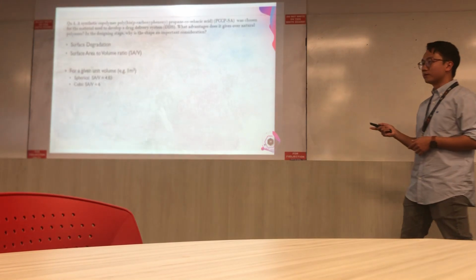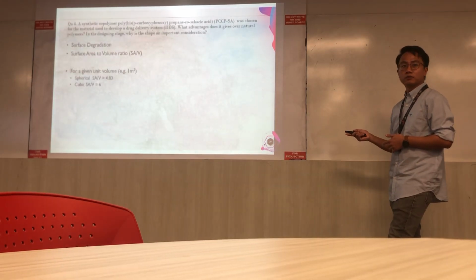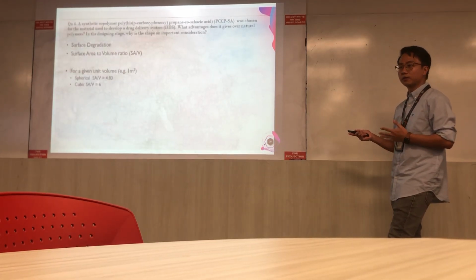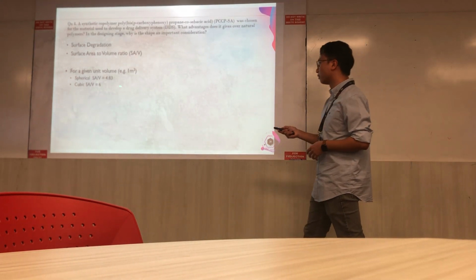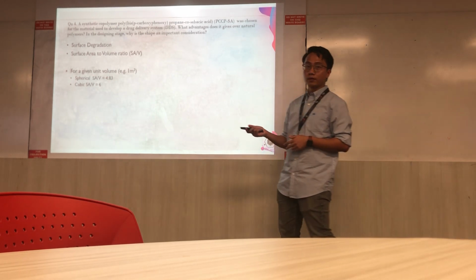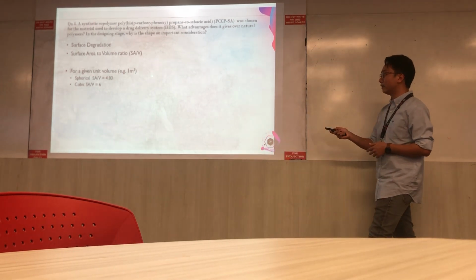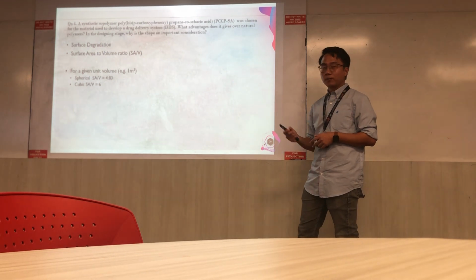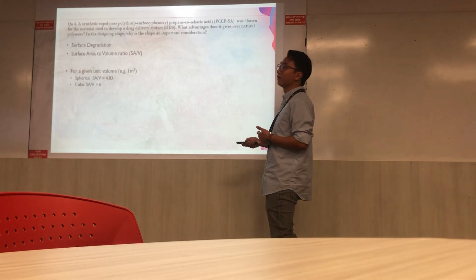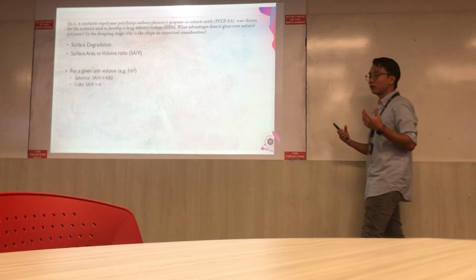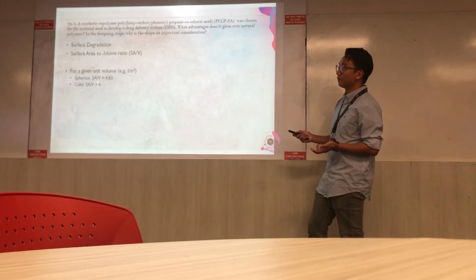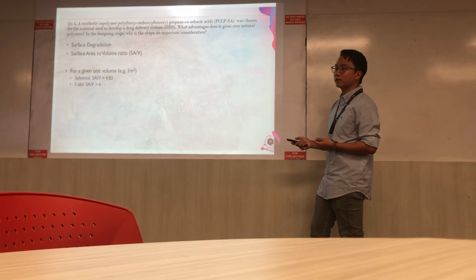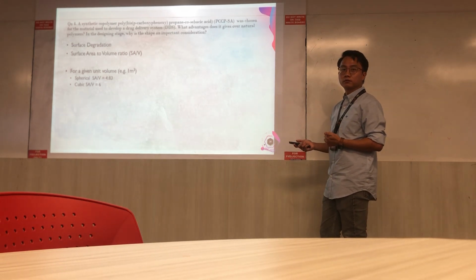Then you find the surface area of the sphere, which is 4 pi r squared, and you realize it's actually 4.83. Both have the same volume, but because of their different shape, they have a different amount of exposed surface area. If I know that it undergoes surface degradation, which one will degrade faster, the cube or the sphere?